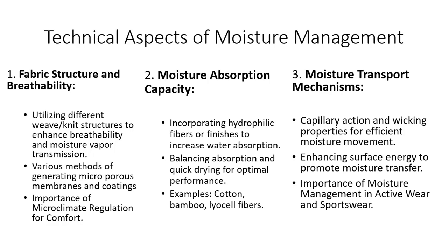So therefore, you can sometimes blend the fibers, hydrophilic and hydrophobic fibers together, or else you can apply certain after finishes to increase the water absorption capacity. And in here, when it comes to the absorption, you need to balance the absorption as well as the drying. It's because we know cotton is a comfortable fabric. Cotton absorbs more moisture, but industries do not use cotton more frequently for active wear.